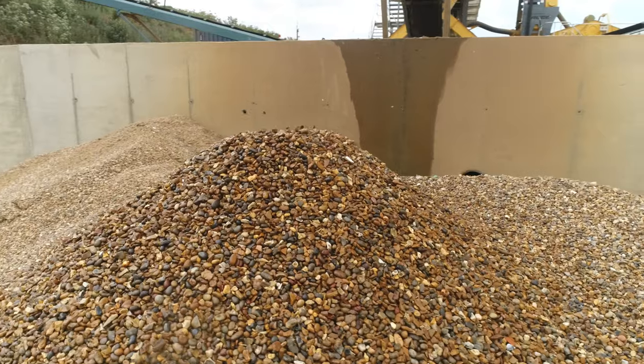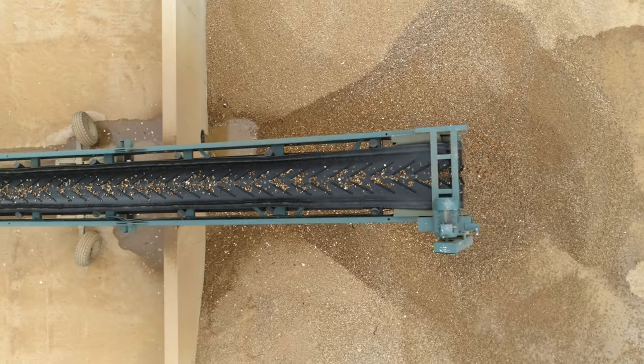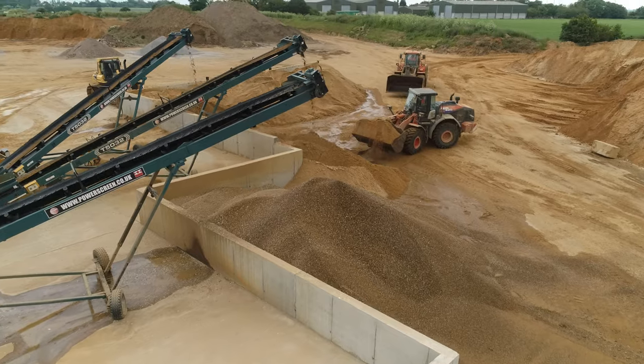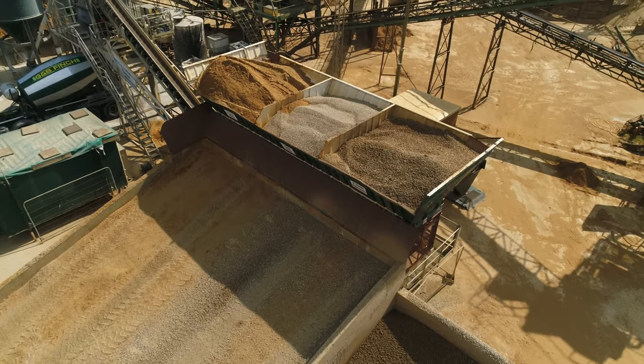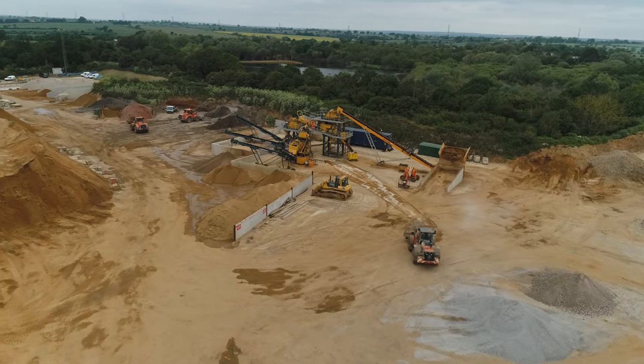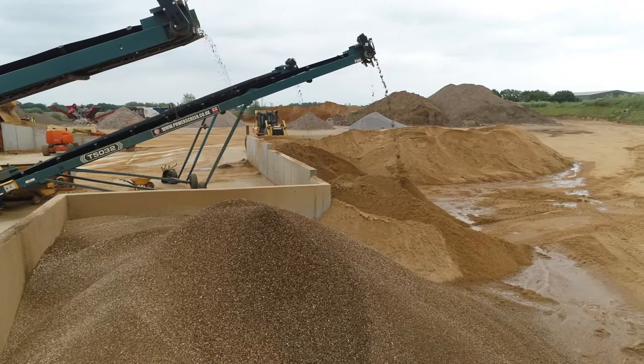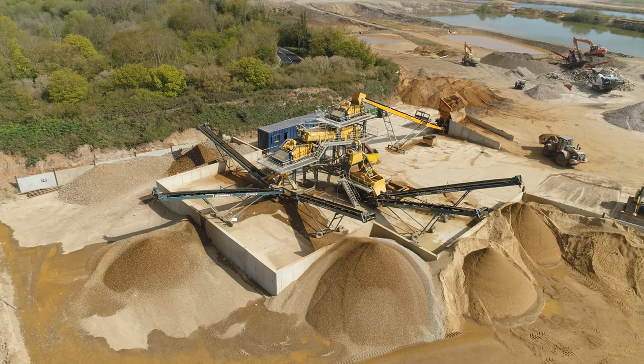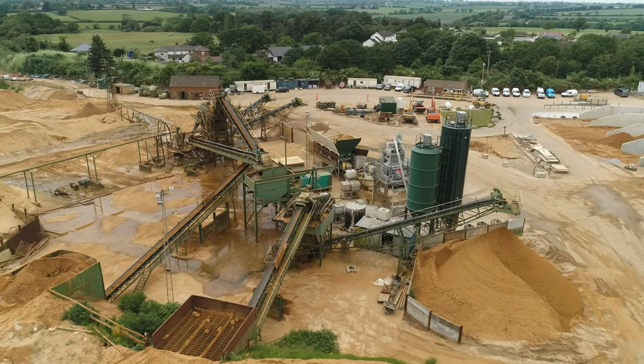That's your oversized there? That's our oversized stuff — that doesn't go into concrete at all. There will be your 10-to-20 millimetre — this is the largest stuff that goes in. And that over there will be your 4-to-10 millimetre. We mix those together. When that's going into the concrete mix, your grading curve of aggregate is 0 to 20 millimetres, and it's that grading curve that creates the strength — the strength and the perfect mix. That's all your separated aggregate there. From there the aggregate is taken over to the stocking bays right by the concrete plant. Let's go and take a look.